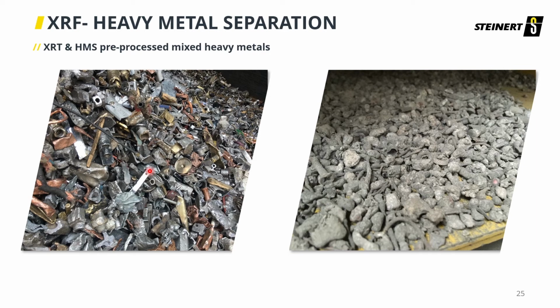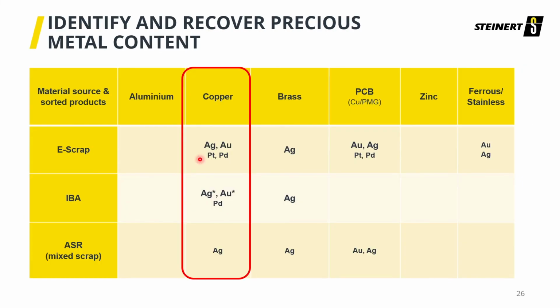Aside from stainless upgrade, what we're going to look at as well is the heavy metal separation. So on the left, what you see is a mixed heavies fraction, maybe off XRT, maybe off heavy media system. On the right, you see a heavy metal mix off IBA, an IBA fraction. And the important thing to note in these fractions is that they do contain precious metals. And when you're using XF, you want to recover those, you want to identify them. So for each different material stream that's coming in, you see different precious metals in that grouping that are common.